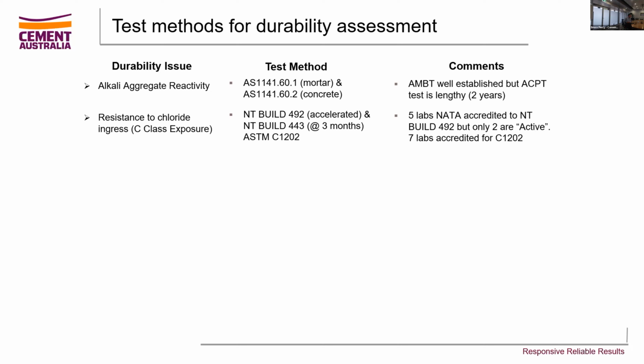So there are three methods which are generally accepted as being used to assess whether a concrete can resist the ingress of chloride. Remember, once the chlorides get down to the steel reinforcing bar, that's when the issues of corrosion begin to occur. Jason touched upon modeling methods, life cycle modeling methods to predict how long it takes for chlorides to penetrate the covering concrete and get down to the steel. But these three methods are essentially designed to compare or evaluate a particular concrete's ability to resist chloride ingress.